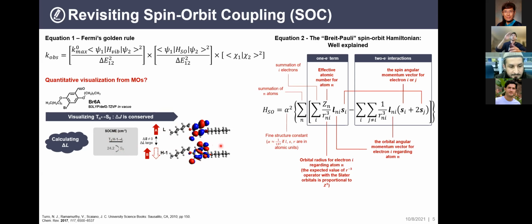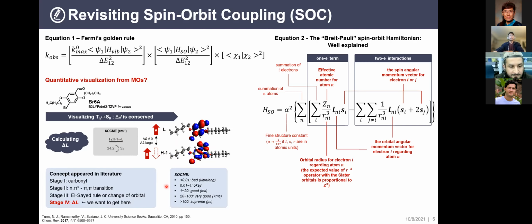So this in-plane change in orbital angular momentum is basically the right-handed rule. So if you are rotating like 90 degrees, you are getting a very large orbital angular momentum change, or angular momentum change in general. So this in-plane to out-of-plane change is going to induce a very large orbital angular momentum change. And that is the reason why for this specific HOMO-1 to LUMO transition, you are getting a somewhat large spin-orbit coupling value. Typically, but unfortunately, people don't really talk about angular momentum, because although I try to make it clear how to visualize that, somewhat clear maybe, generally speaking, it's very hard to visualize that.